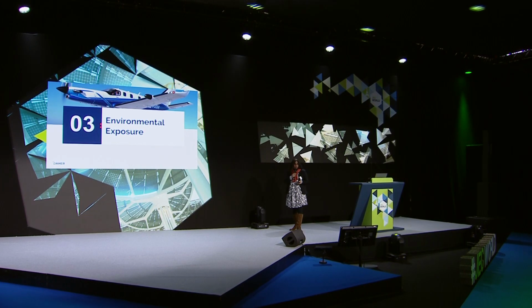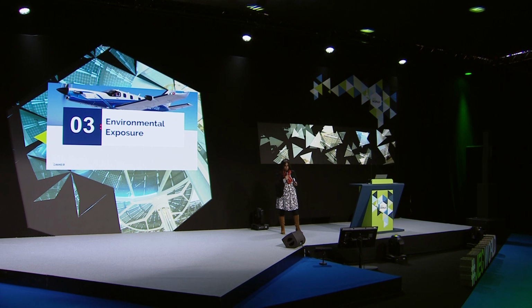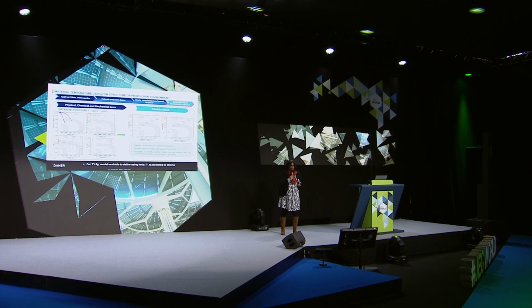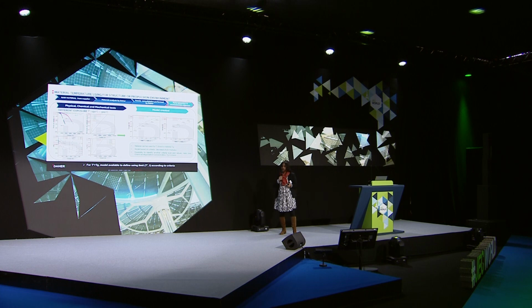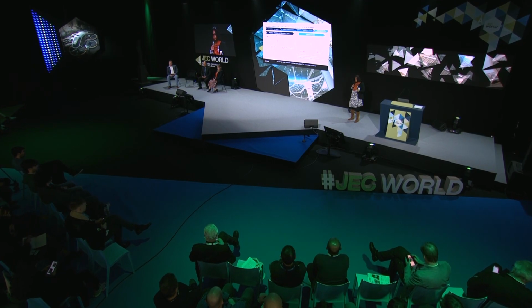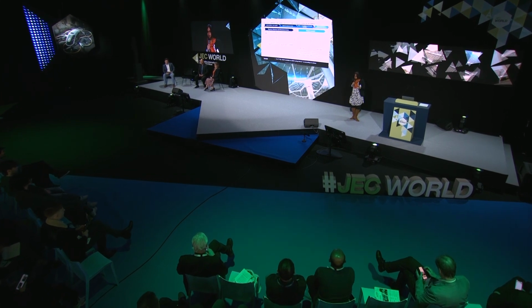Let's have an overview of the environmental exposure of the material. So we have put some consolidated material at different temperatures and different times, and we have seen if there is any mass loss, any chemistry change, any flexural change, or a Tg change. All this data we have gathered, and we have built a model which helps us to understand, according to the thickness of the material, what is the time and temperature where there is no degradation of the material.